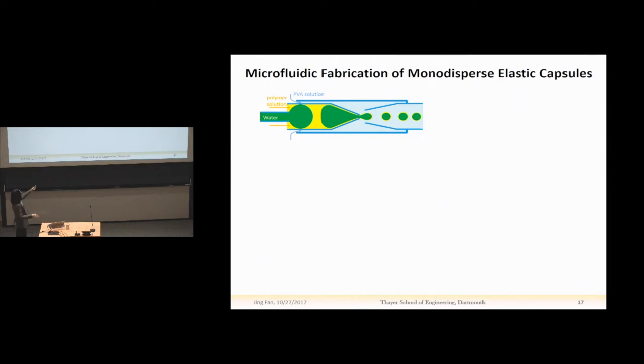We use microfluidics to, first of all, generate some model double emulsion droplets with a very thin shell. It's actually the device that I showed at the very beginning of the first slide. So it works in this way. We have two tapered round capillaries. The left one is called the injection capillary, and the right one is called the collection capillary. And they coaxially assemble in a square capillary. Besides these two, we also have a much thinner capillary injected into this injection capillary like this.